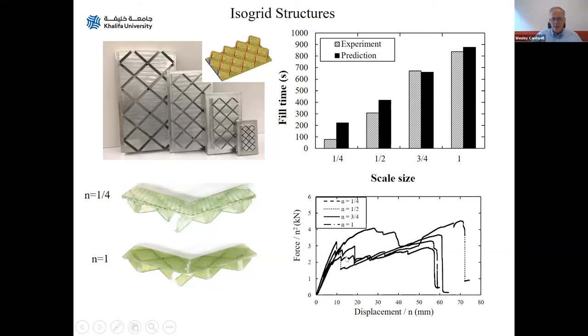But again, these are our force displacement plots. Although you can't see because they all seem to be black in color, this is our quarter scale sample here. It doesn't behave terribly well, and that's really due to some of the problems that I mentioned earlier in the actual manufacturing, but the other 3 scale sizes do pretty well here. And these are our fractured samples after testing. So these are really quite complex structures, but there's our N equals quarter, there's our N equals 1. This one here has got fiber fracture along the middle here, so has the large one here. You can see how the quarter scale sample, which was quite a small sample, has exactly the same type of failure as the large one.